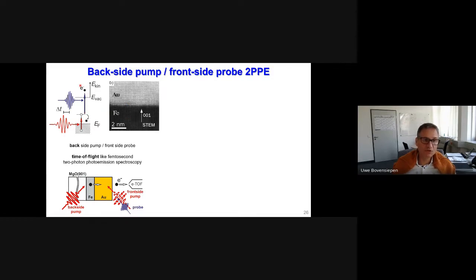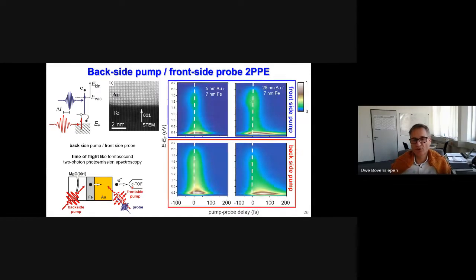Now, the probing that we do is we ionize, we take out the photoelectrons, and we analyze the energy. So this is another way how to represent this. We have the backside pump, we excite hot electrons, which we inject into gold, and then we probe here on the front side with an electron spectrometer. For comparison, we can also bring the pump to the front side and look directly at these propagation effects. So we do a kind of a time of flight like femtosecond 2-photon photo emission spectroscopy.